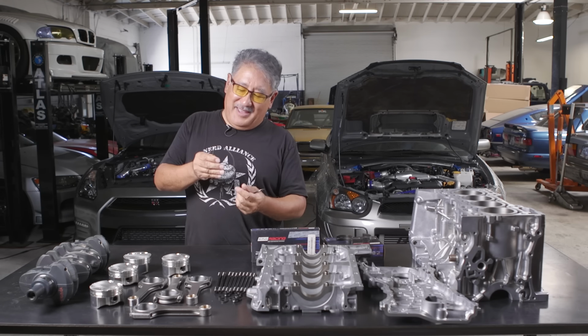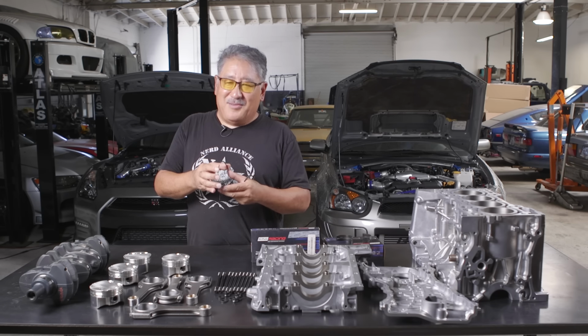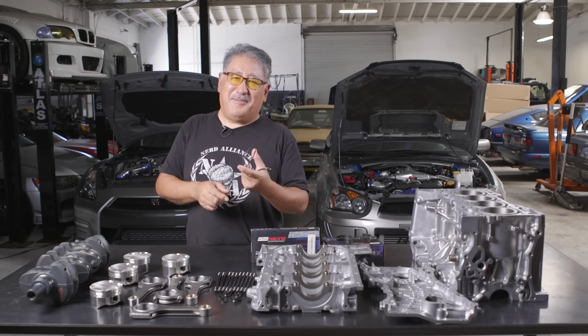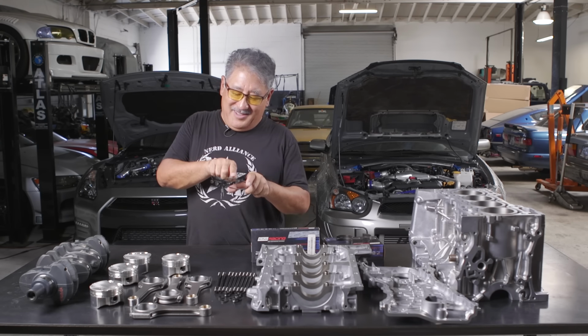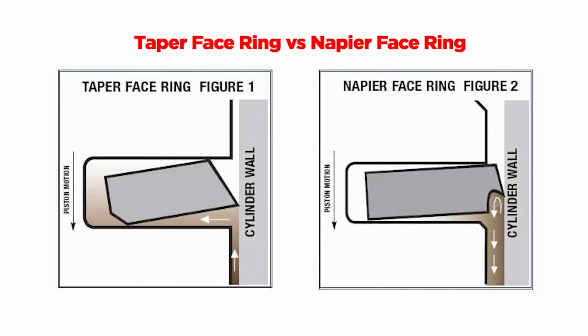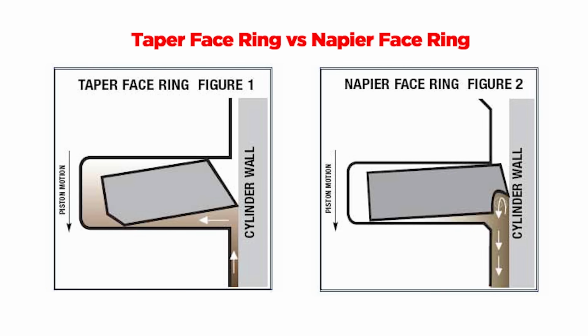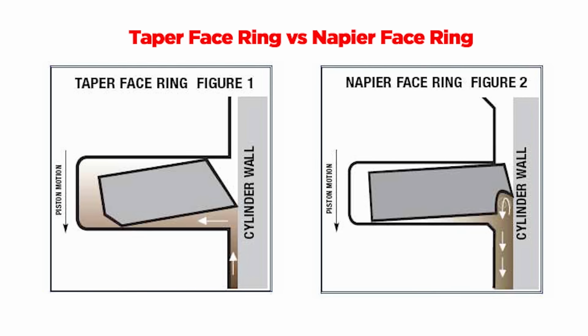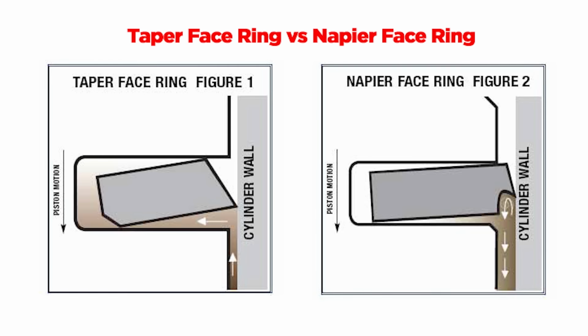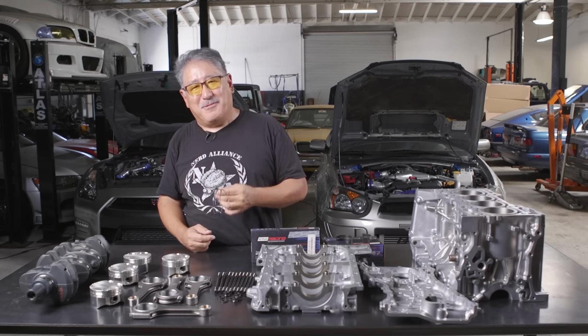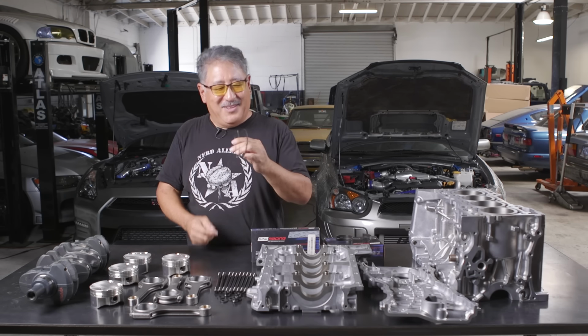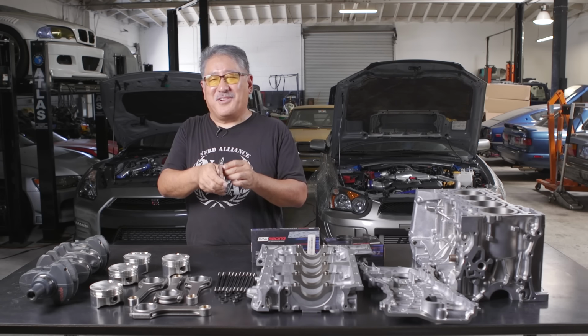So with a nitrided ring, it's small, has this slippery outside, and is really hard, so it lasts a long time. The number 2 ring is like a ductile iron. What's tricky about this is it has what's called a Napier profile. A Napier profile has a little hook in there. The hook actually helps trap gas to put some more radial pressure into the cylinder wall for better sealing. It also has a really thin edge that wears into and conforms to the cylinder wall really quickly, which gives you fast break-in. Most JE pistons have a Napier second ring, and even though these are really thin, really low tension, really low friction rings, we've never had a durability or an oil burning problem.